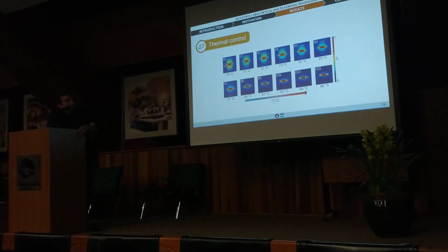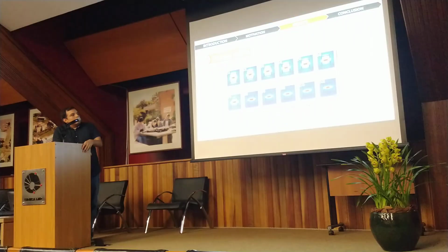The first part is the thermal control. What we found here is that when the temperature increases, we have a transition from the optical mode to the plasmonic mode. As you can see, this is the main part of the electric field that is parallel to the Z axis. We can see that at all of these temperatures, most of the electric field is confined in the slot waveguide.